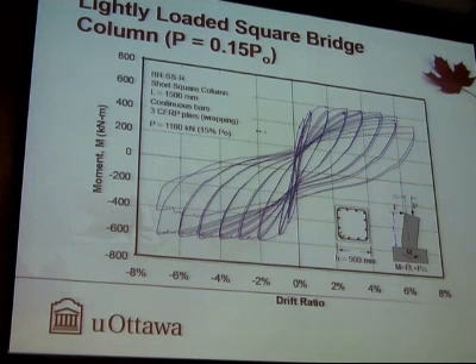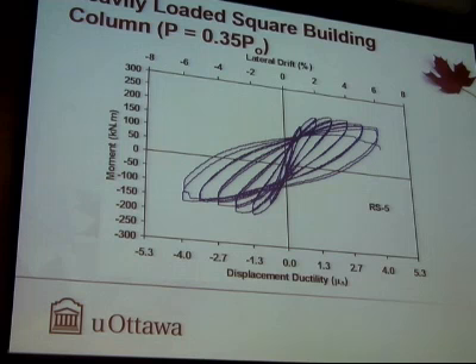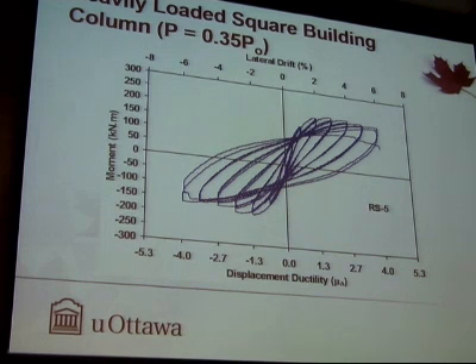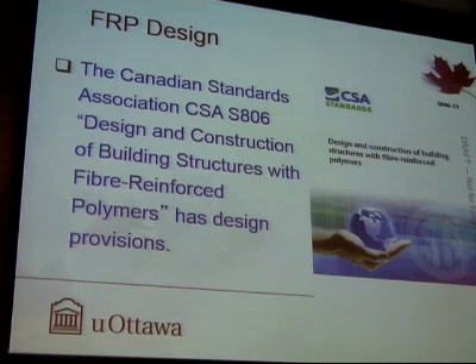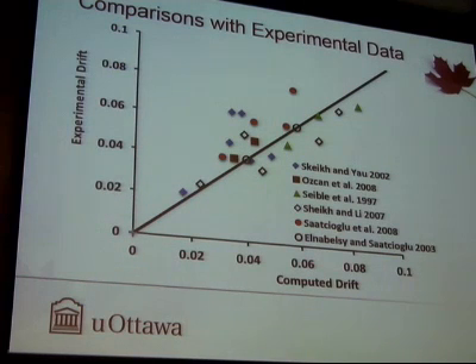And here's an example of a square bridge column this time, retrofitted with fiber jacketing, and it was able to go 4 to 5% drift. And then here is a building column which is subjected to 35% of P naught, which is typical of building column axial load level. And here we were able to rupture the transverse reinforcement. The current, or I should say previous, design approaches did not consider axial load as a parameter for FRP jacket design. And hence a displacement-based design methodology was developed as a function of axial load and lateral drift capacity, and has been incorporated in CSA standard S806 in its 2011 edition. It does provide a fairly decent comparison if you solve for the drift capacity, which is a design parameter, and compare it with experimentally observed drift capacity.